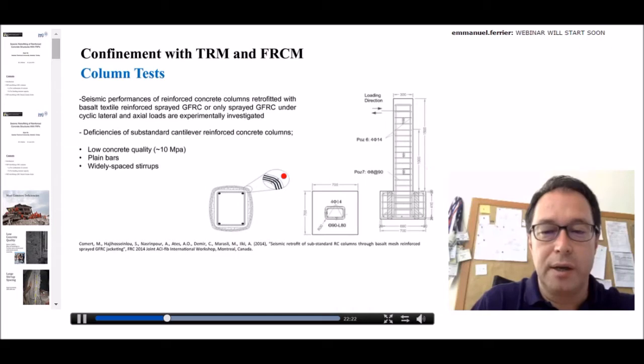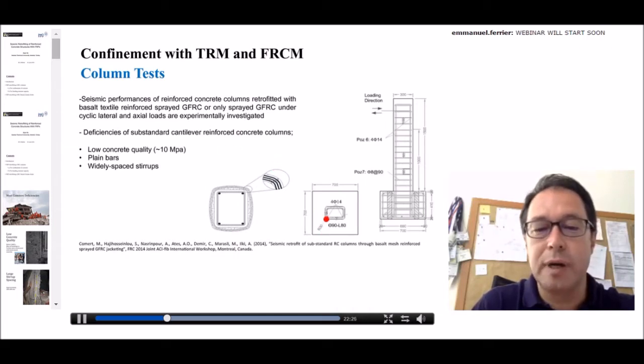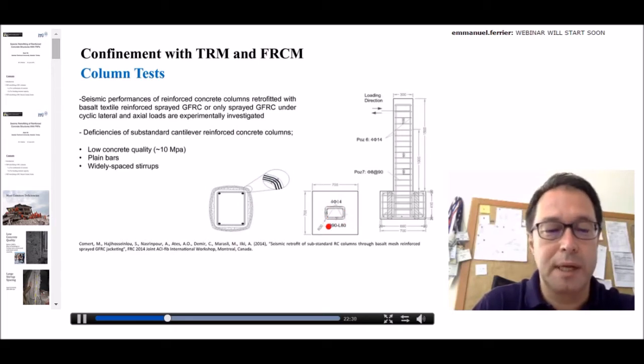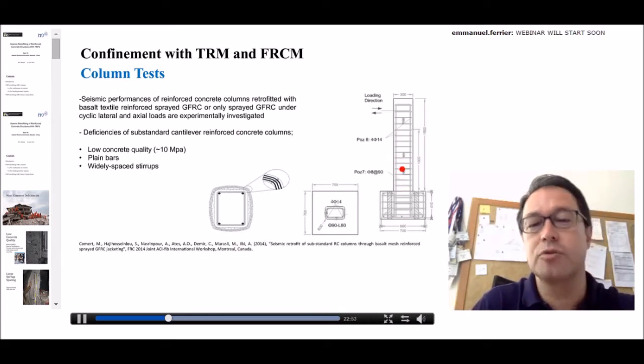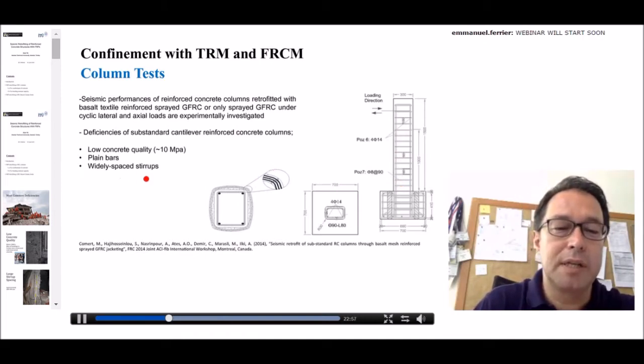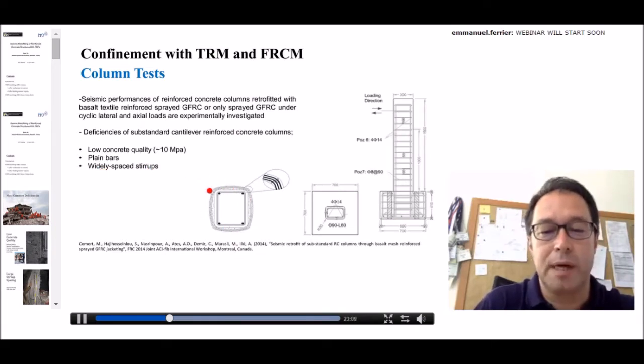That is how we applied it in case of columns. These columns were 20 by 30 centimeters. Not full scale, but I could say nearly full scale. And they were constructed with 10 megapascal concrete, substandard concrete. We used plain reinforcing bars, both for longitudinal and transverse bars. And we had different types of transverse bar spacing, going from 60 millimeter to 180 millimeters. This photograph shows one with 90 millimeter stirrup spacing. But as I said, first, this kind of retrofit was much more effective when we look at the behavior of widely spaced stirrup cases. So here you see how we applied this kind of application. And I should repeat again, this application is done by spraying the concrete, like kind of shotcrete.